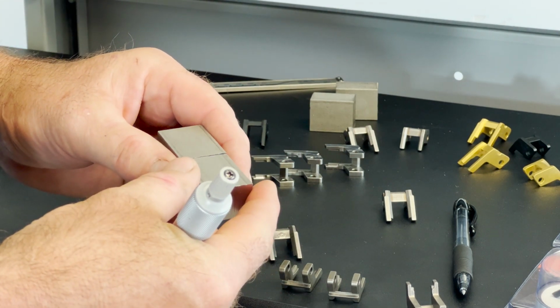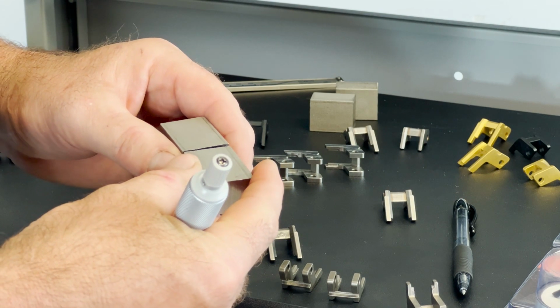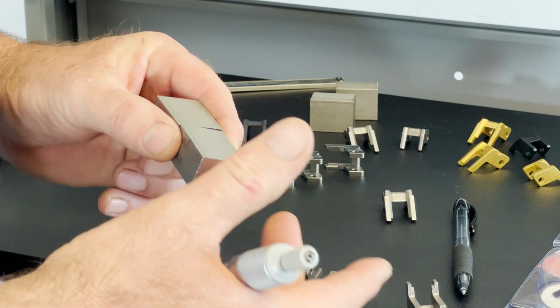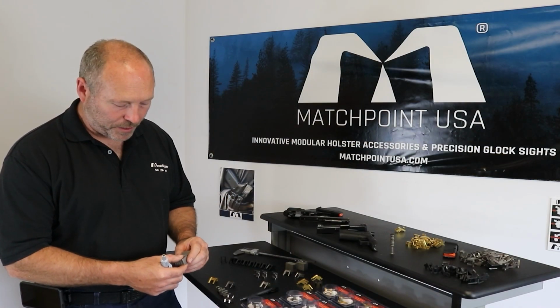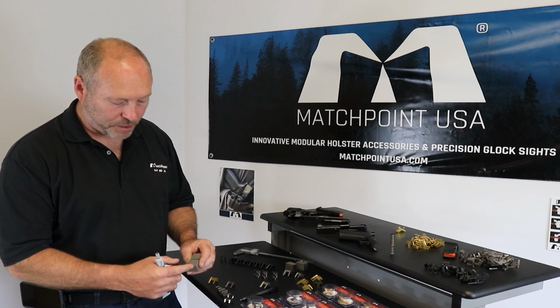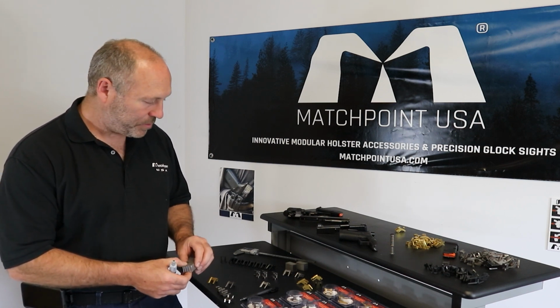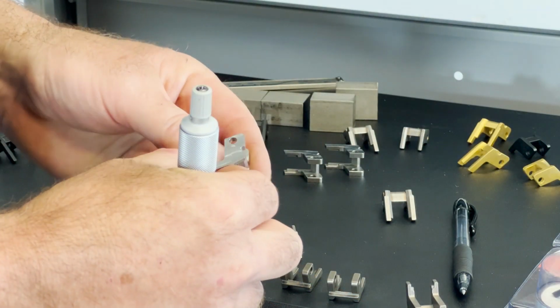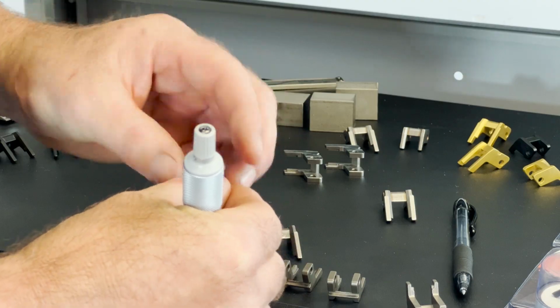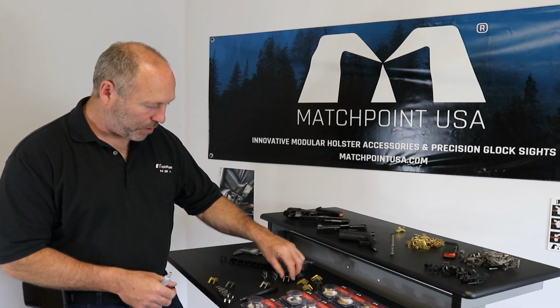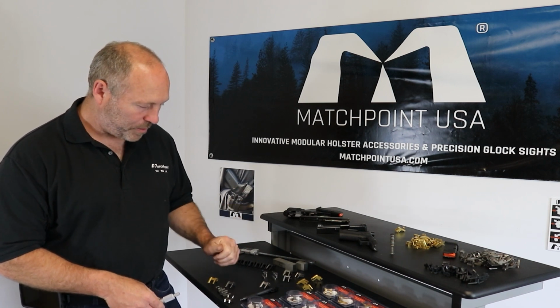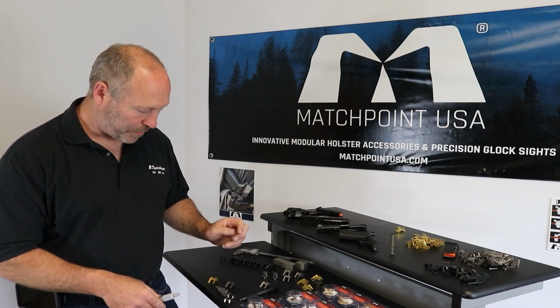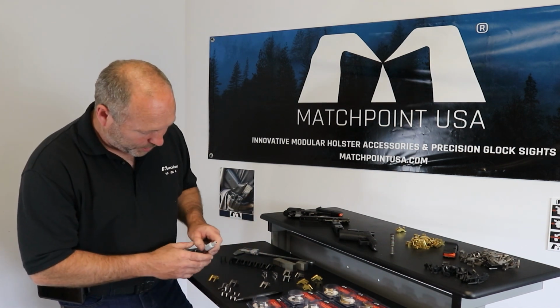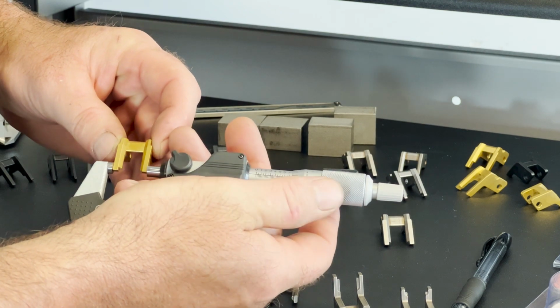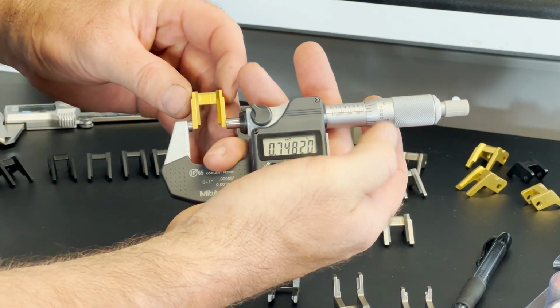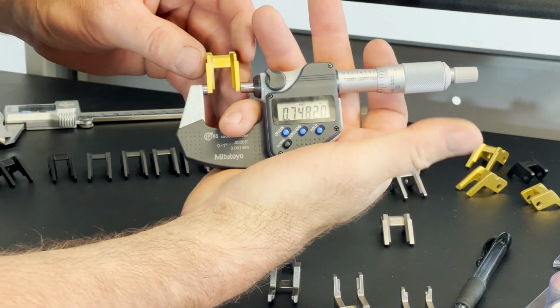If you can imagine these bars, these are basically like an extrusion. They're hot drawn, so they don't have the really nice surface finish on the outside, and they're not quite as precise, but in this case we completely mill that away. So we end up with a part that looks like this off of the CNC machine. Then they're tumbled, deburred, heat treated, and so forth to get you the finished product, and then finally plated. So when you go measure a MatchPoint billet block, you got 748 thousandths and 2/10.